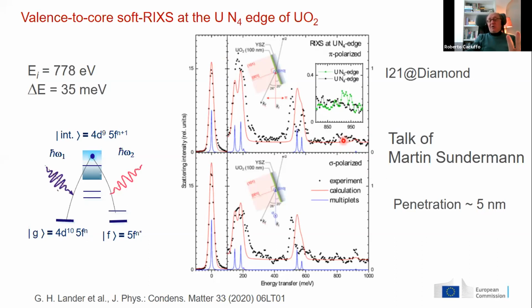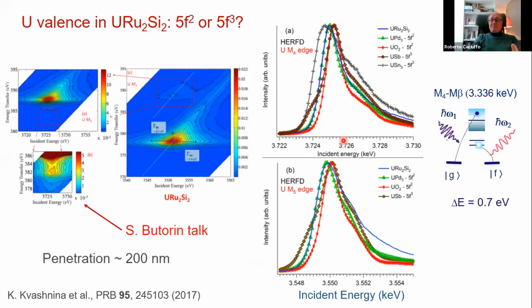At the N4,5 edge with 778 electron volts, the penetration is of the order of a few nanometers. Then this is certainly a surface technique. On the other hand, at the M edge, the penetration is of the order of 200 nanometers, and then the technique starts to essentially probe the bulk properties of the system.